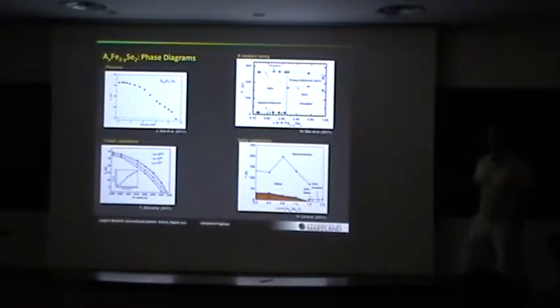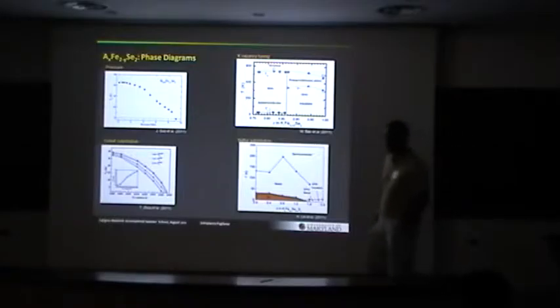These are all very recent results. For the parent compound iron 79, there's already some debate about whether there are vacancies in the iron in the parent compound, which causes the disorder and makes the superconductivity emerge. Which compound are you talking about? Iron 79, but not 1,2,2. You mean iron 1, selenium 1? Yeah, something like that. That's a completely different compound. So it's kind of become a 1,2,2 system.